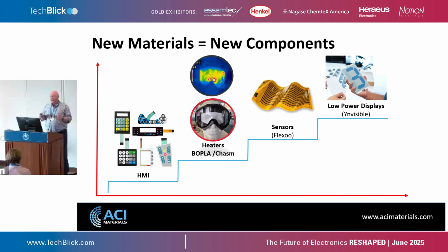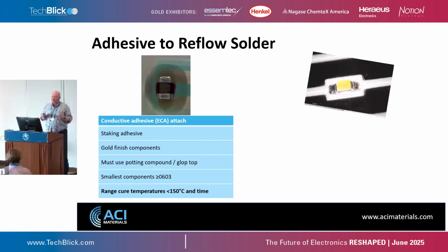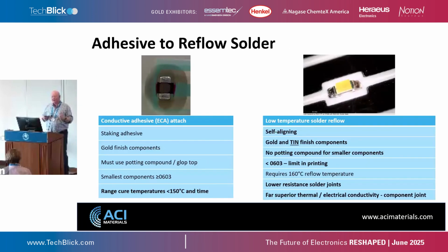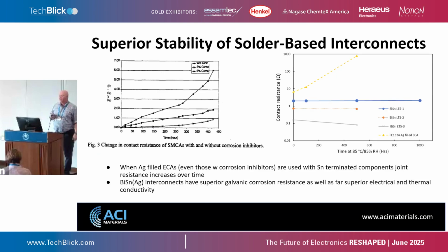But really, one of the things that needs to be is connection to standard components. And printed electronics up until now has been all conductive adhesive attach. So with our semi-sintering materials, we can low temperature solder, and this has a lot of benefits. You know, the components are going to self-align. You can start using tin finish components as well as standard gold LEDs, for instance. We don't need potting compounds over the top to have good solder adhesion, get to smaller components, lower resistance, better thermal. So really being able to reflow, we're now getting into the mainstream of electronics assembly.